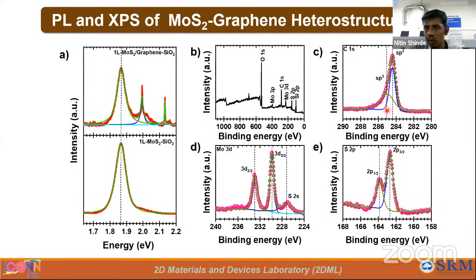We are getting two peaks around 284 and 285. This is sp2 hybridization of the carbon atom, and this is sp3 hybridization of this carbon atom. And this is the well-known spin-orbit splitting, the two bands 3d5/2 and 3d3/2, and this is sulfur. We are also getting this very nice spectrum. Also, the splitting of this Mo 3d, we are getting 3 electron volts. It is well known and reported for MoS2 graphene structure.